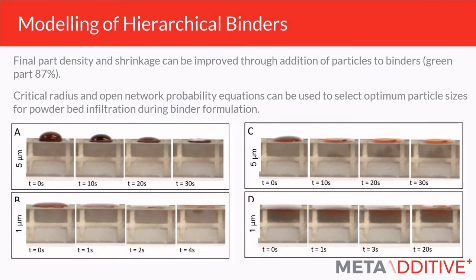And this is some very quick experiments that we used to validate the mathematical model that we developed. First of all, we've determined that from that model, the green part densities we can get are 87%. But it also shows us that if our particles are too large, they'll just sit on the top. And that's what you're seeing here on A and C. You're seeing a droplet of binder onto a powder bed. This is a copper binder onto a titanium powder bed, so that you can see the material difference. If the particles are too large, they just won't penetrate the powder bed and they get stuck on the top.